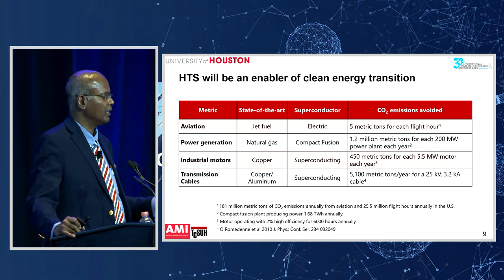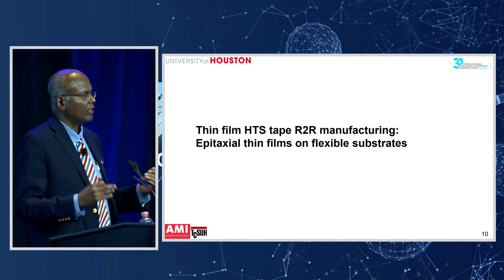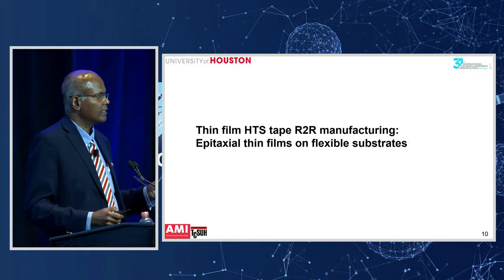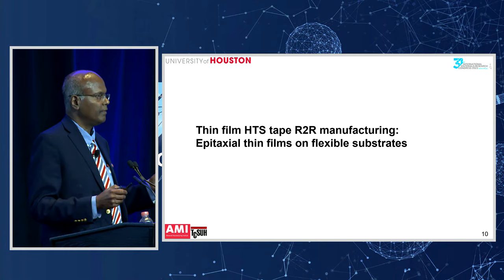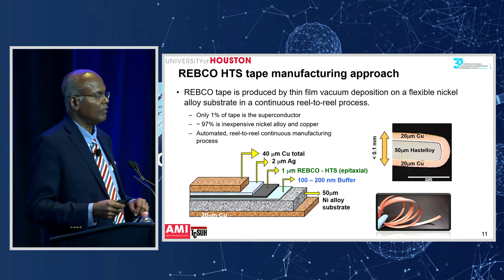So with that as a background, let's talk about the actual material itself. These are thin film superconducting tapes. Like I said, it's a unique technology in that these are epitaxial films on a thin, flexible substrate, and the tape is made by roll-to-roll manufacturing. This shows a schematic of the superconducting tape. You can see that it consists of many layers. We start off with a nickel alloy called Hastelloy.